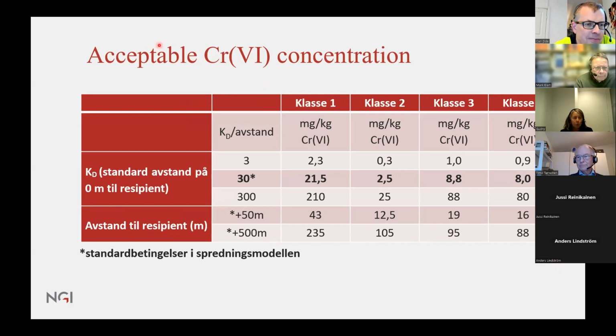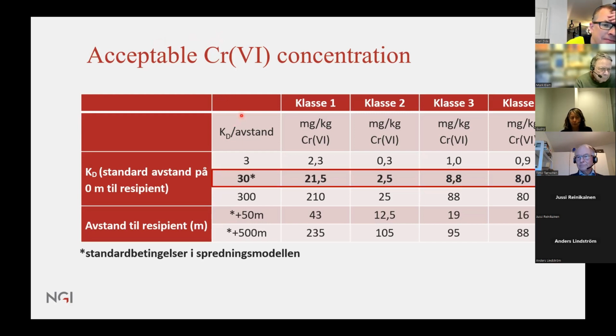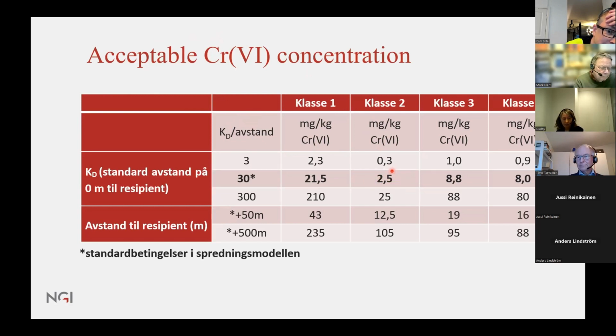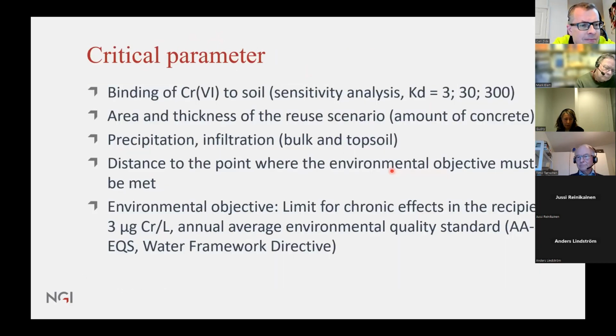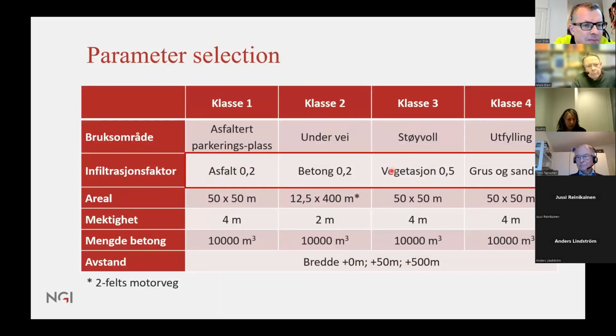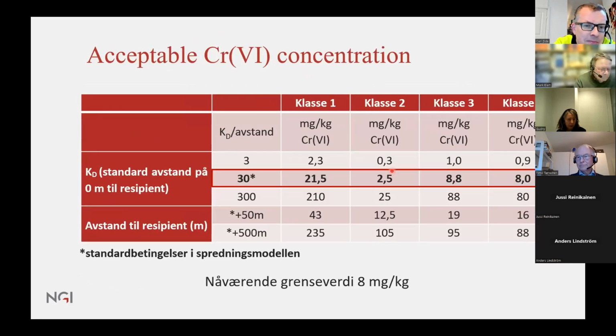So what kind of acceptable chromium concentration did we get? If you look at when you're using the default values for the different classes, we see that it's actually the road construction which gives the lowest value. And it has to be said that the guideline value we have in Norway today is 8 milligram per kilogram. That's the solid phase, right? What we have calculated here is back calculated from the maximum allowed concentration in the recipient, which was not groundwater, it was a small river.